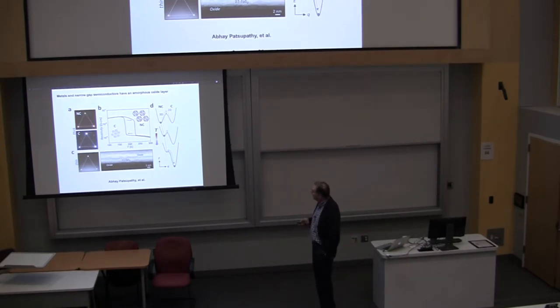One observation that Abhay Pasupathy made a couple of years ago was that as soon as you get away from semiconductors and you start looking at narrow gap semiconductors and metals, the surfaces of these materials become rather unstable, and they tend to form amorphous oxide layers. And he observed this in many materials. And here's the case, this is like tantalum disulfide. And so that becomes a problem when you want to make devices, right? If you have this amorphous oxide layer on top.